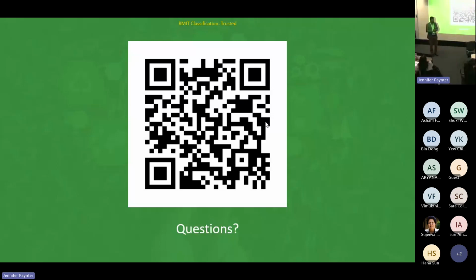Thank you. And how far have you progressed? Yeah, for the moment, we have already developed the predictive model for compressive strength, and it's been validated with laboratory testing experiments. Up to 95% accuracy, we can predict the compressive strength up to now. And the next step will be expanding our model to incorporate mechanical performance parameters like flexural strength, split tensile strength, and elastic modulus of geopolymer concrete.